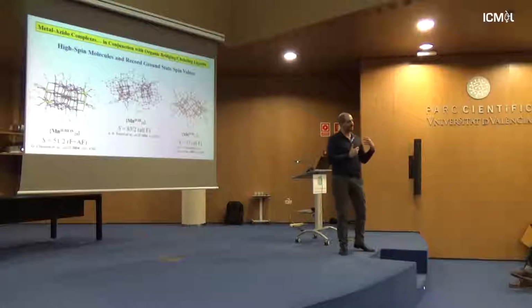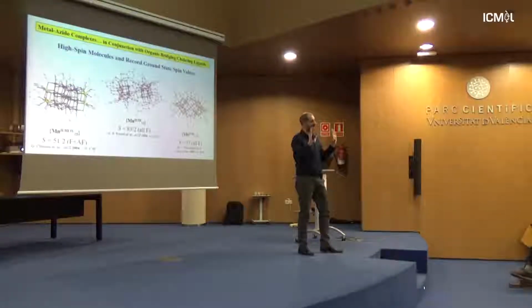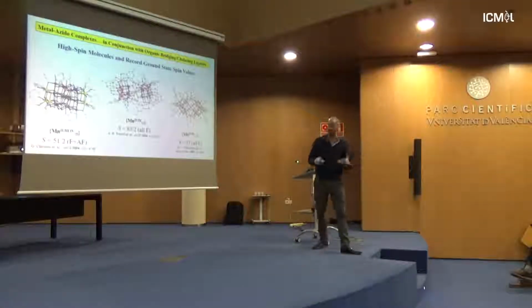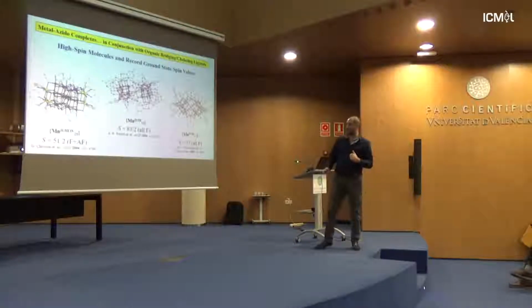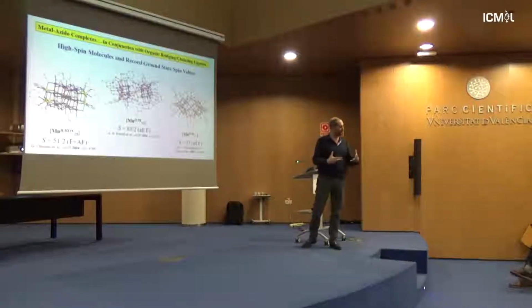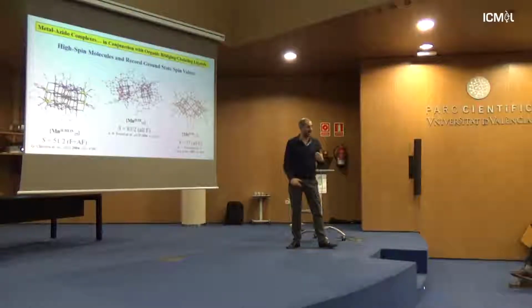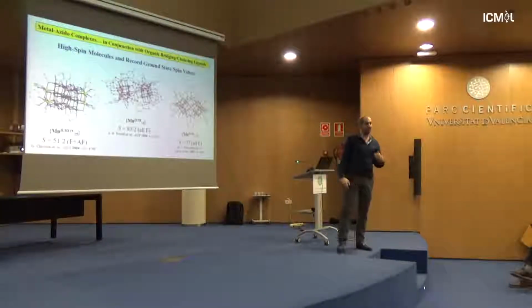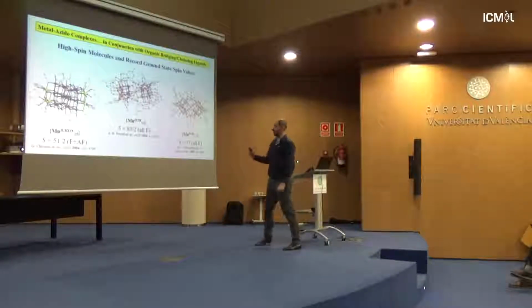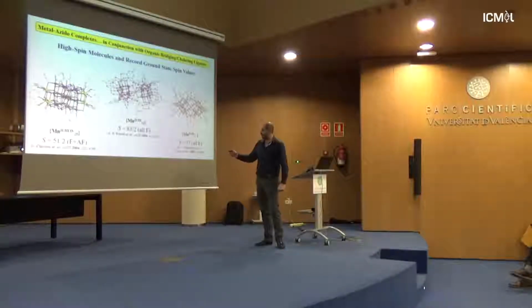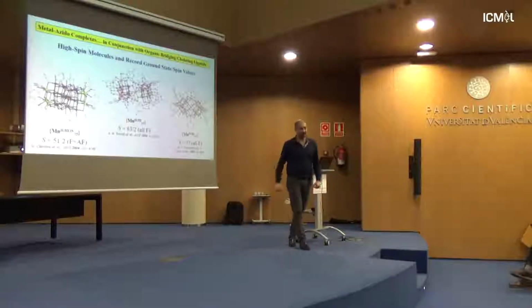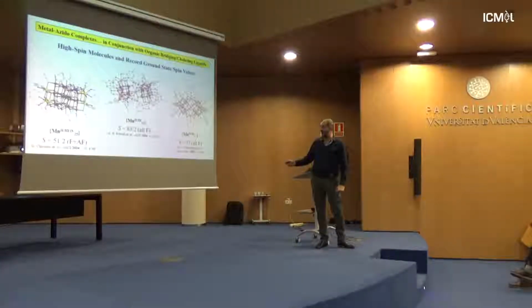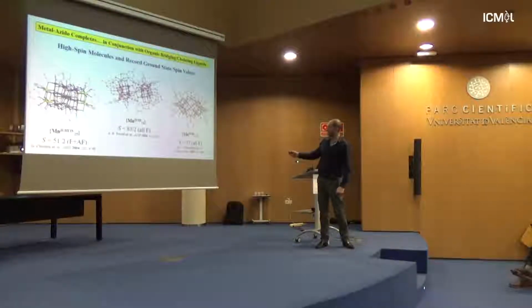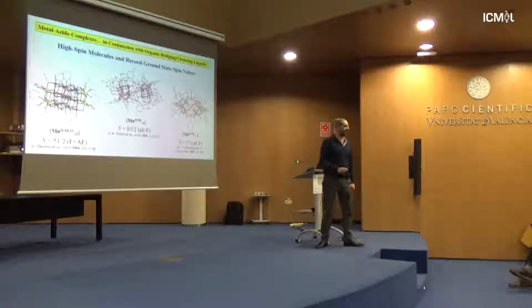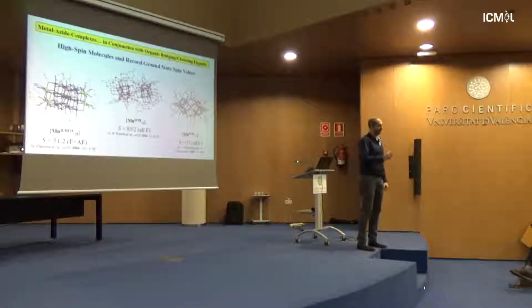And this is actually proved by looking a little bit at the literature. And you find some very interesting compounds which essentially you can say, all right, here we are. Okay, it's already there. We don't need to really develop a new strategy. And as you can see here, those 3 representative examples, these are cluster compounds, lots of metal ions, with tremendously large spin numbers, with tremendously large number of unpaired electrons. However, only those 2 compounds, the manganese 19 of Annie Powell and the manganese 17 of Tassos Tassiopoulos, have azides, organic ligands, oxido, and still the maximum spin ground state possible for that system.